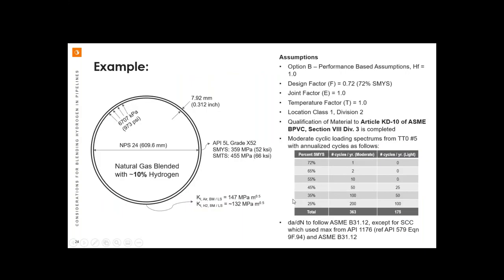So before we begin, we're going to need to take a look at a particular pipeline configuration for the calculations. So let's take a look at that here. On the left side of the presentation, you'll see that we have an NPS 24 pipe, and we want to introduce just a small amount of hydrogen, let's say up to 10%, at 6,700 kPa. We have a 7.92 millimeter wall thickness, API 5L grade X52 pipe.